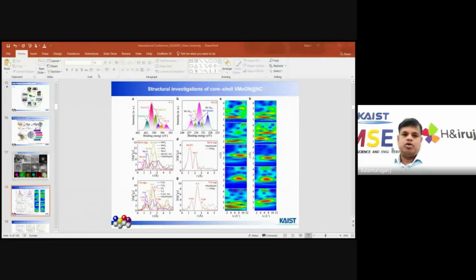After confirmation, we do the structural investigation by XPS analysis. You can see different types of nitrogen networks, like pyridinic, pyrrolic, and graphitic nitrogens. We also see many vanadium-nitrogen bonds and molybdenum-nitrogen bonds. From the studies, you can see the pyrrolic nitrogen is higher than pyridinic as well as graphitic, so our material contains more pyrrolic nitrogen. We also see molybdenum with 2-3 different oxidation states, maybe 0 plus, 4 plus, and 6 plus. And we also do the local structure by XAFS analysis.